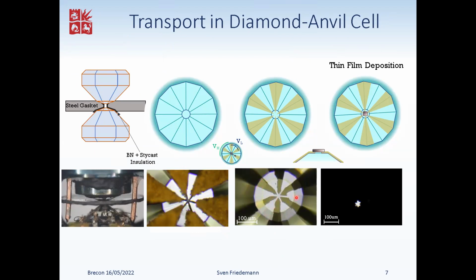It's a 50 micron, no, this is a 100 micron culet. And this is then what you see once you look through the hole of the gasket on top of this mask. So you can just about see the tips of that sample. The thin film deposition itself requires a bit of optimization, but we've got that very well under control now. Very good adhesion of the electrodes, and barely ever problems that they short to the gasket or something like that.